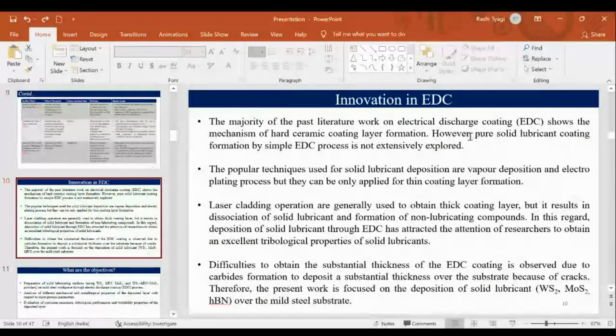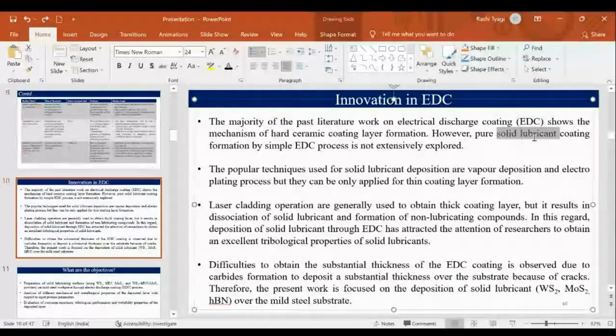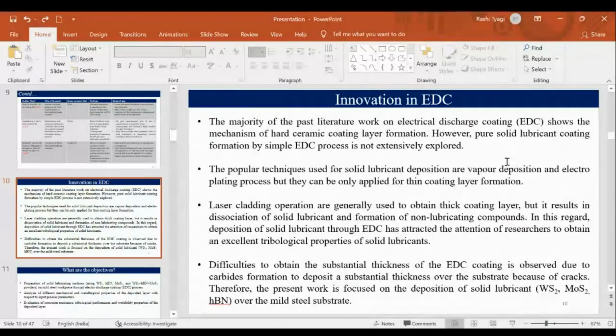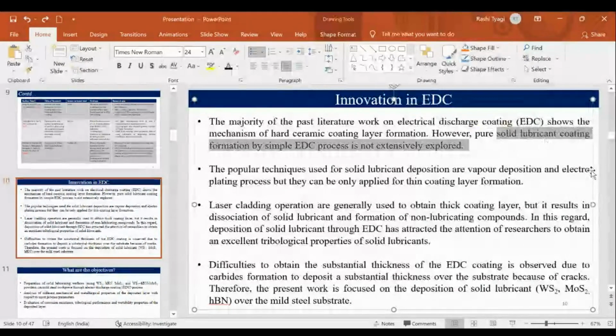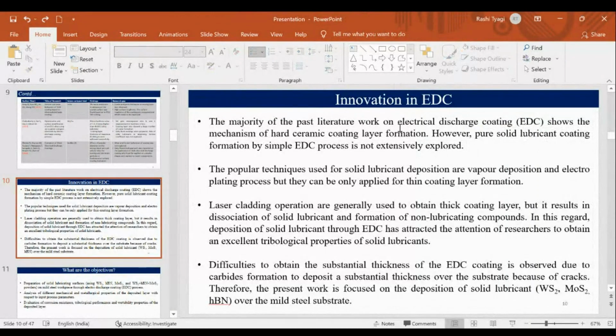As we have seen, pure solid lubricant coating cannot be deposited. Briefly, solid lubricants can provide excellent tribological property. So if you want to obtain excellent tribological property, you can use solid lubricant powders. It's far better than hard powders if we can utilize their whole properties, because solid lubricant sometimes disintegrates into other compounds, so it is difficult to utilize a solid lubricant coating. We will see how we can obtain complete deposition of the solid lubricant without disintegration by using the simple EDC process. Different techniques are used, but they can be used only for thin coating layer formation. EDC can be used for thick coating layer formation, 2 mm thickness, and it has already been used. Laser cladding operation is performed to obtain the thick coating layer using solid lubricant powder, but it is observed that there is a formation of non-lubricating compound.